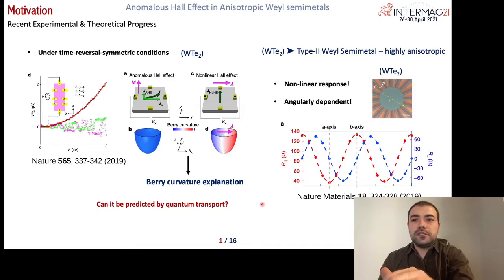In the last two years, a significant number of papers published in the subject of anomalous Hall effect or non-linear Hall effect. It is well known that broken time reversal symmetry eventually leads Hall signal in semi-metallic conductors. However, these experiments show that even under time reversal symmetric conditions, Hall effect and even non-linear Hall effect can be observed. And this experiment clearly detect the angular dependence of anomalous Hall voltage.